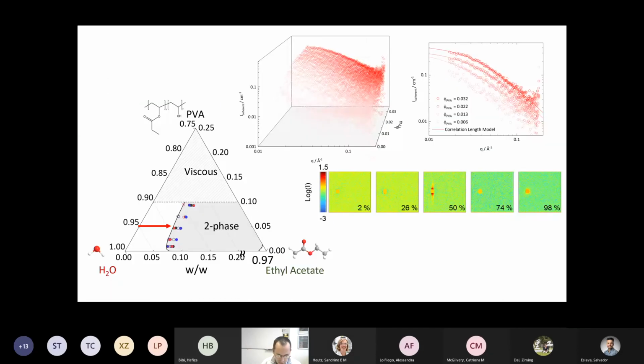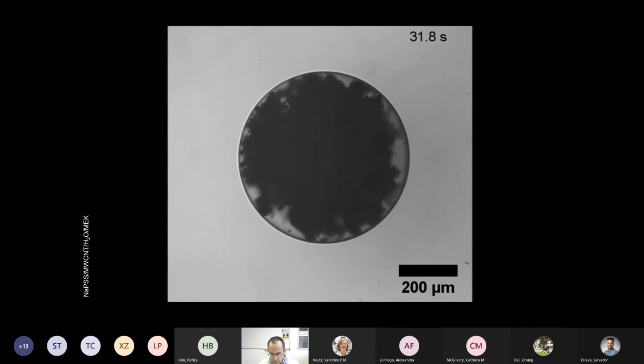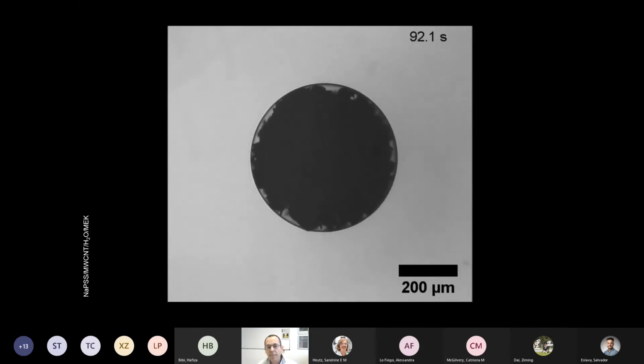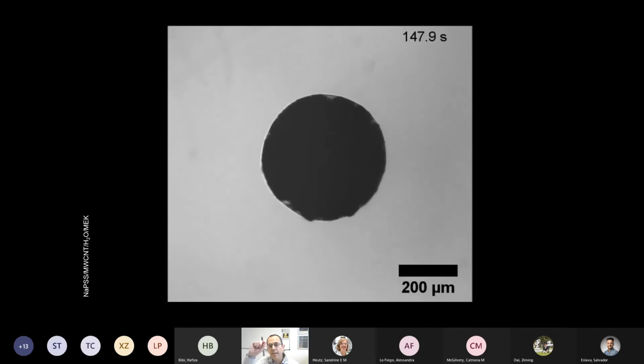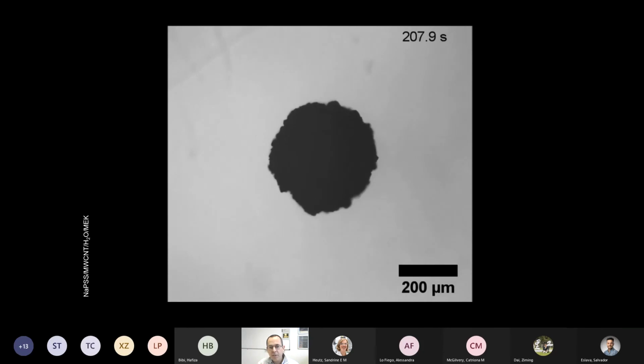The same thing for the polymer. So I can come from the dilute solution and watch, as a function of time, the transformation between the dilute and the concentrated solution, and eventually the formation of the particle. So this is what happens if I have a system that is non-interacting. I've created a thin skin, and here I've suspended a bunch of nanotubes. I've effectively just wrapped these around, a bit like shrink wrap for packaging, a bunch of material within a very thin polymer skin.